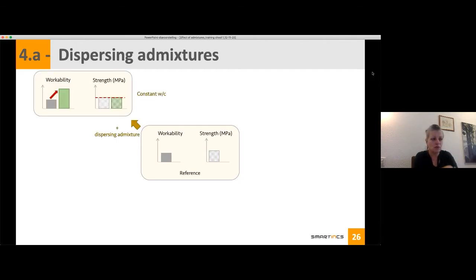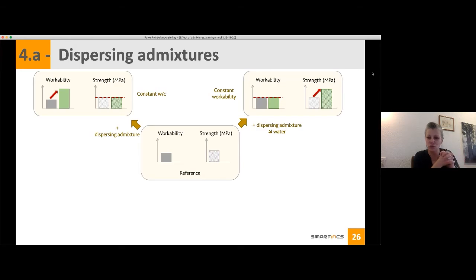To summarize, this will be your reference concrete. And then if you really want to target an increase of workability, you keep the same mix and just add some dispersing admixture, so your strength won't be much affected, but you will have an increase in your workability. Now you can think, okay, I want to have higher strength, but I can work with a constant workability, which means you will add your dispersing admixture, reduce your water content, and this will translate into a higher strength development in your mix.